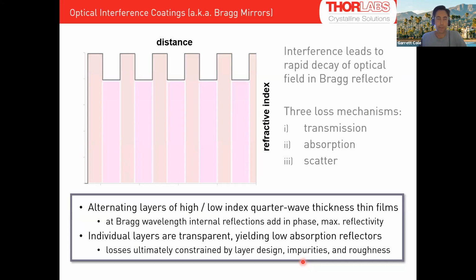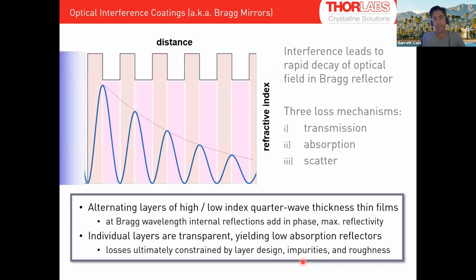So let's go a step deeper into the interference coating structure. This is a plot of refractive index as a function of distance or position in the mirror or in this multilayer. This can go on to near infinity, say many periods terminating on the substrate, but I've cut it off here. And if you have light incident from the left, if you've designed, like in this example, a simple Bragg mirror, so a bunch of quarter wave alternating high and low refractive index materials, you'll see an exponential decay into that mirror structure, and you'll see a strong counterpropagating reflection there. And again, the point is these individual materials are transparent, and you have these weak Fresnel reflections at each interface, but these will constructively interfere and add together to give you a high reflectivity at the so-called Bragg wavelength.